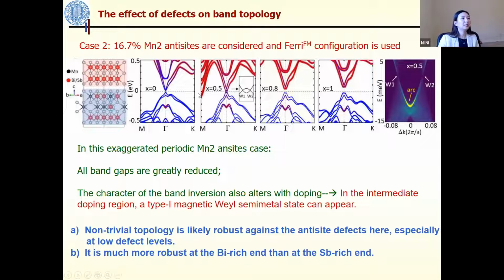In this exaggerated periodic manganese-2 antisite case, you can see all band gaps are greatly reduced. But what we can see here is that the band inversion still persists up to the intermediate doping regime. So the DFT calculation actually shows some robust band inversion here, which again suggests that the topology is likely robust against the antisite defects, especially at the low doping levels. And for this doping level, the band structure calculation even suggests a magnetic Weyl semimetal state.